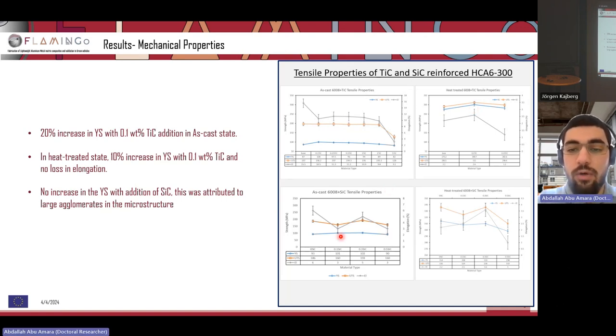And with the additions of silicon carbide, we weren't able to achieve any increases in the yield strength, neither in the as-cast state nor in the heat-treated state. And we attributed this to the large agglomerations which we saw in the microstructure.